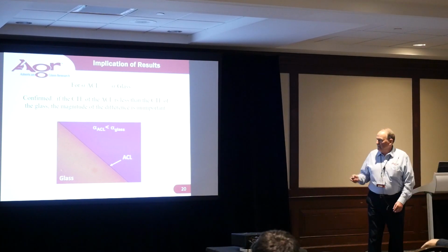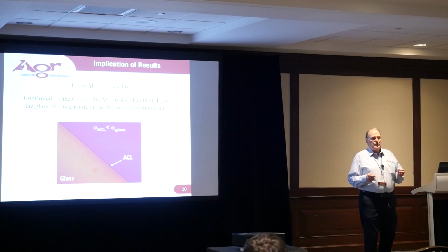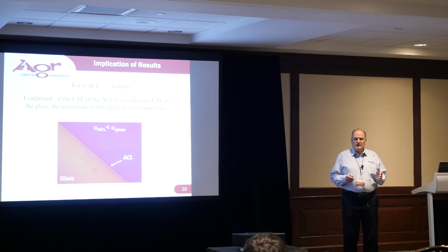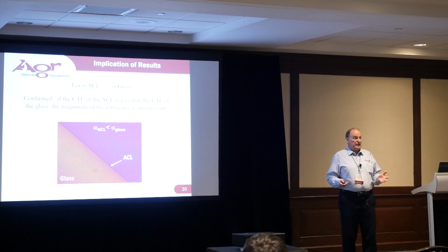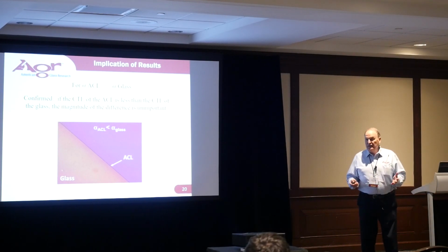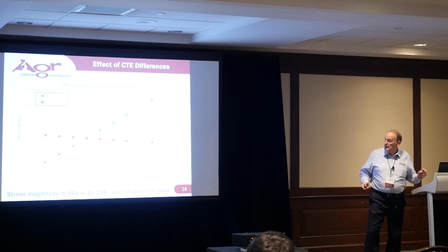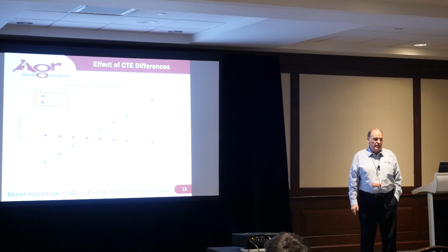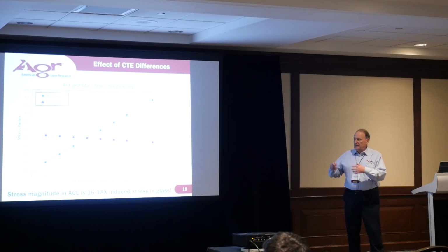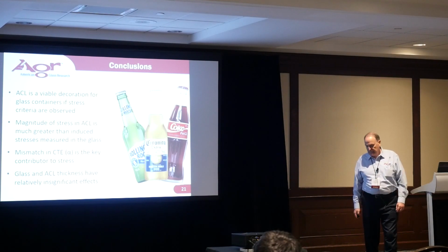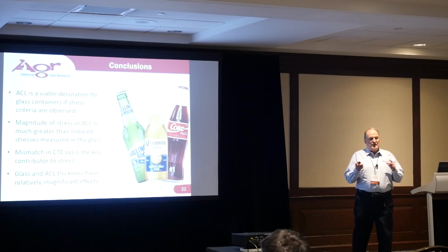Now, what was interesting is that when we looked at these papers, not just Ray Andrews, but others, they never really had firm data, but rather it was based on anecdotal evidence that they were seeing from their practical experience. It's quite valuable. And they were seeing that if the coefficient of expansion of the decoration was less than the glass, it rarely ever produced any problems. On the other hand, if the coefficient of expansion of the ACL was greater than the glass, then that level of mismatch became very, very important. This is now some data that confirms the anecdotal practical evidence of very smart people over the years. So, the factor that is important is that mismatch in the coefficient of expansion.